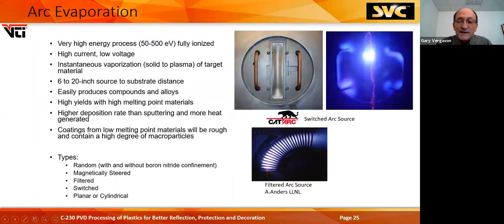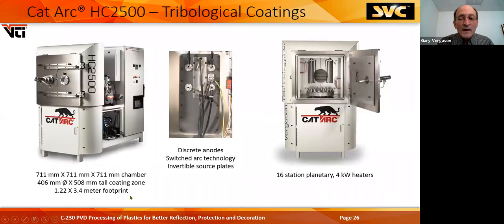And this is our switched arc. So we literally switch the arc power supply connection back and forth on this to drive that arc back and forth, which gives us smoother coatings and much more highly adherent coatings. This is a planar arc source, but you can also have cylindrical, just like in sputtering. Arc equipment is primarily used for tribological coatings for wear and corrosion resistance. And this is the backside of our arc source, and this plate can be inverted to set the process up in any kind of configuration you want on the inside.